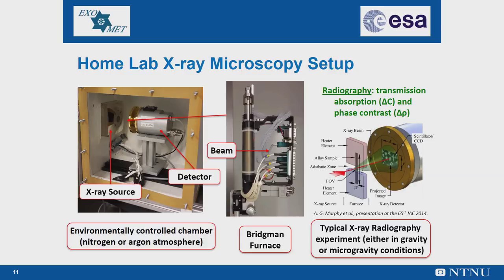In the case of directional solidification, the formation and evolution of the microstructure is detected through both transmission absorption and phase contrast, namely through differences in composition and density between the liquid and the microstructural constituents. The solidification of the metal is recorded and digitalized. A spatial resolution up to 4 micrometers can be achieved under particular circumstances, meaning every pixel has a size of 4×4 micrometers. Subsequent image processing through specifically developed routines can significantly improve the quality of the recorded radiographs.